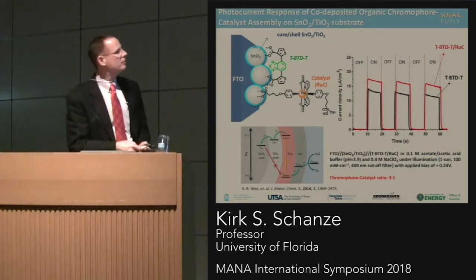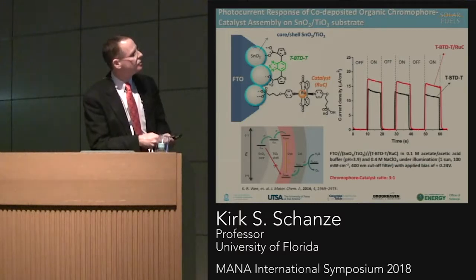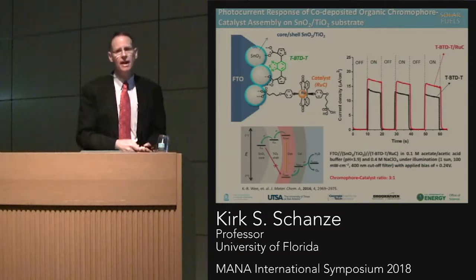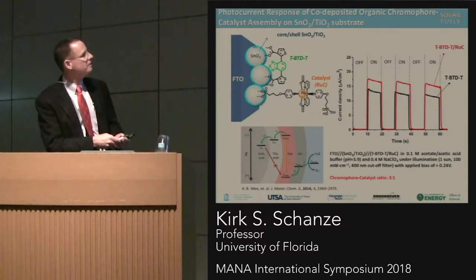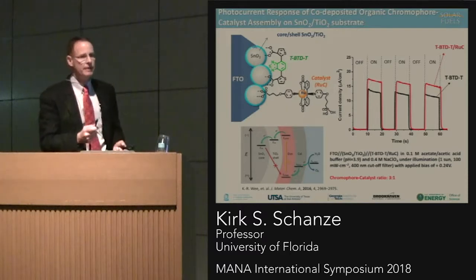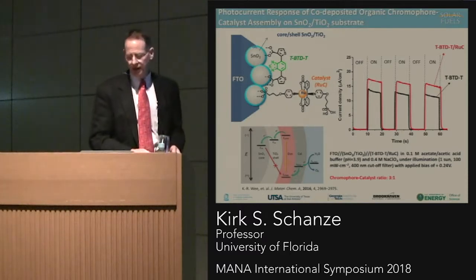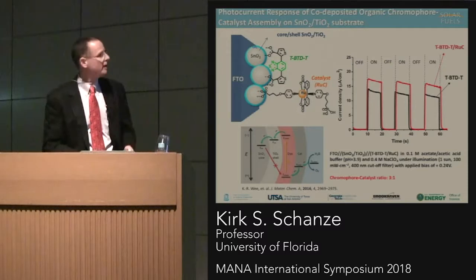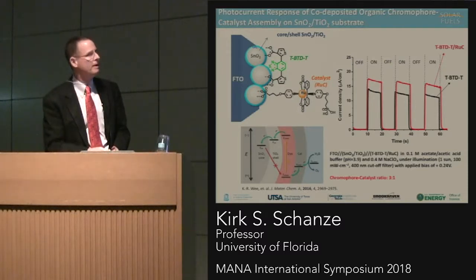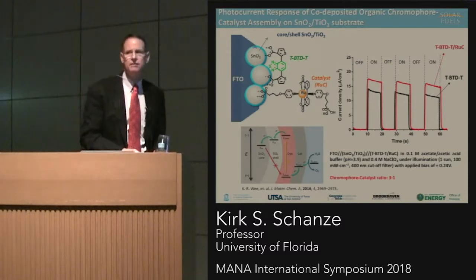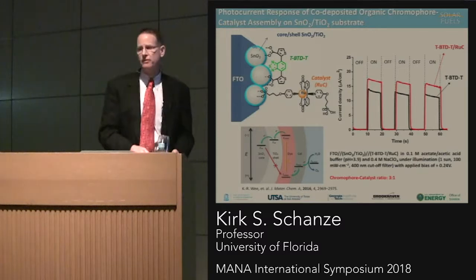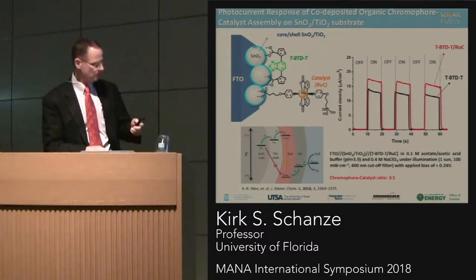There are some problems with this system, and you can see that there is a drop-off in the photocurrent, and that has to do with instability of the dye due to its reactivity when it becomes oxidized. And that's been quite a focus of some of our recent work, and it's clearly one of the issues that needs to be addressed in the future going forward if we're ever to apply these in working photoelectrochemical systems.